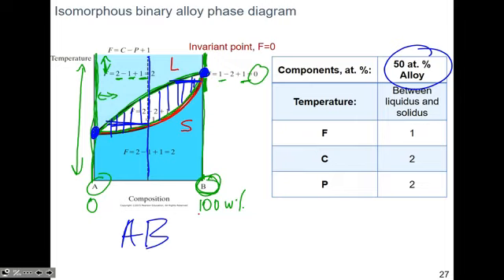And so what's happening is you have this mixture AB right here, and then you're starting to cool. So every phase diagram, start from the top, cool down. You start from the top, you cool down, and at some point it's all liquid, and then you hit the liquidus line. It starts solidifying. You're starting to now form some solid of AB. And then you solidify some more, transform more of that liquid into solid, and then right here is when that solidification is going to go to 100%. And right below that temperature, just like a degree below, you're going to get 100% solid, and now you're in the all solid region. Any liquid that you had will have solidified 100%.